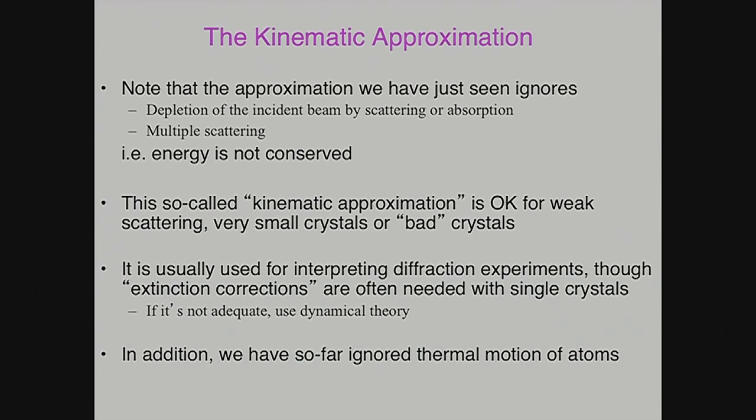Another note of warning, everything that we've talked about up till now, even though I haven't done it formally, I've sort of introduced it in a somewhat hand-waving way, is something called the kinematic approximation. It's or the Born approximation, it's the same thing. So you'll see those words, kinematic approximation or Born approximation. It's essentially a perturbation theory. It does not include multiple scattering, right?